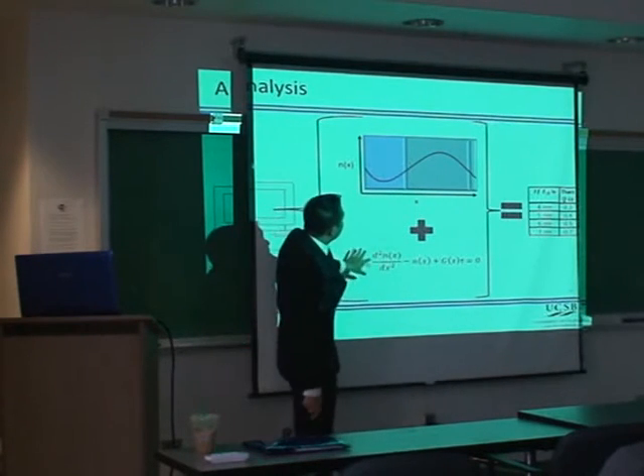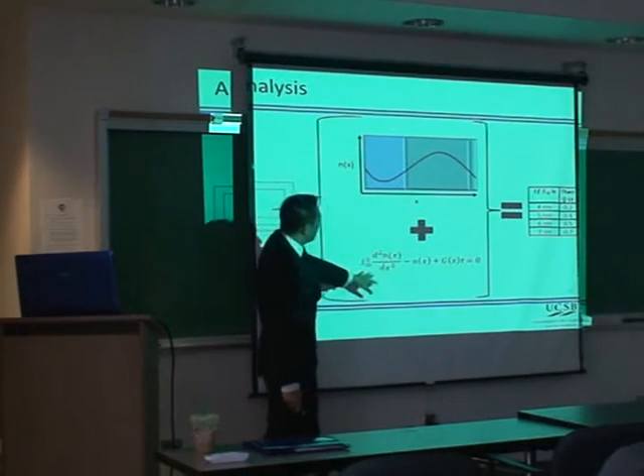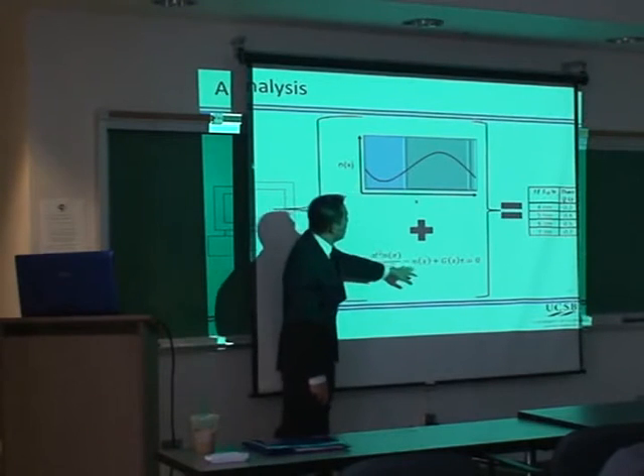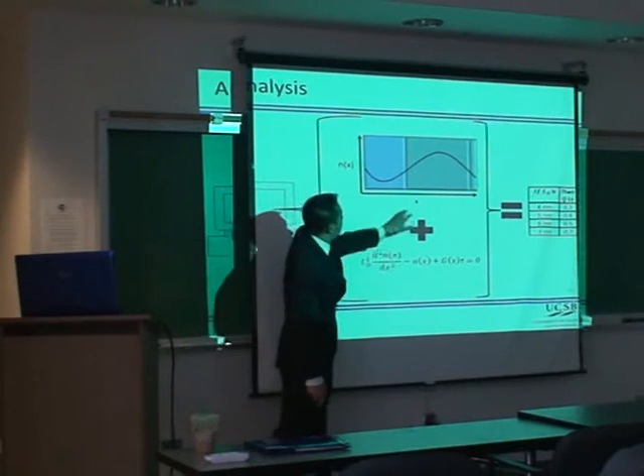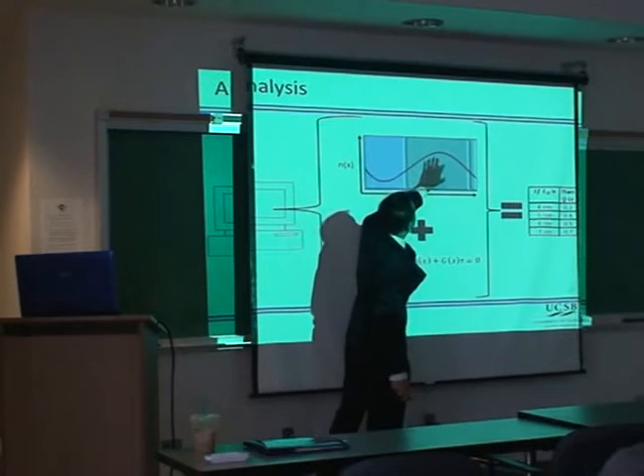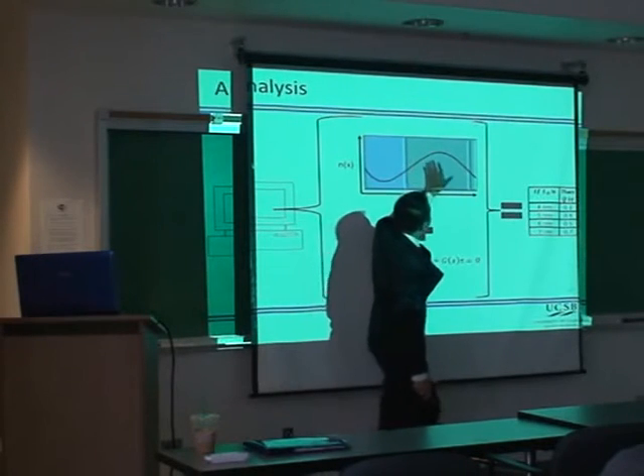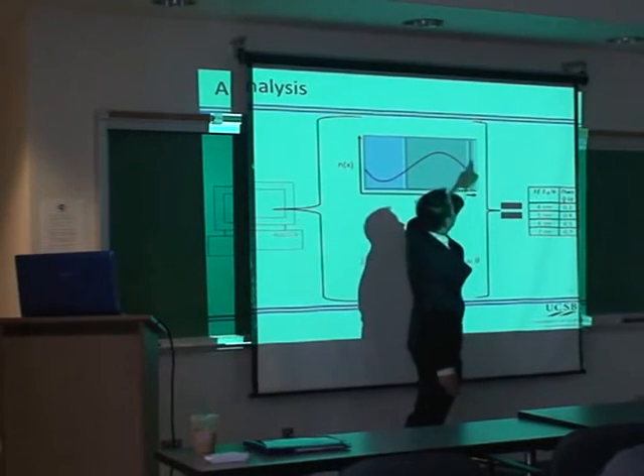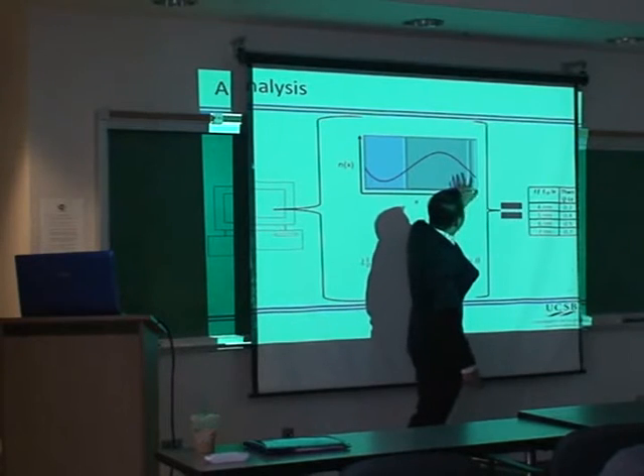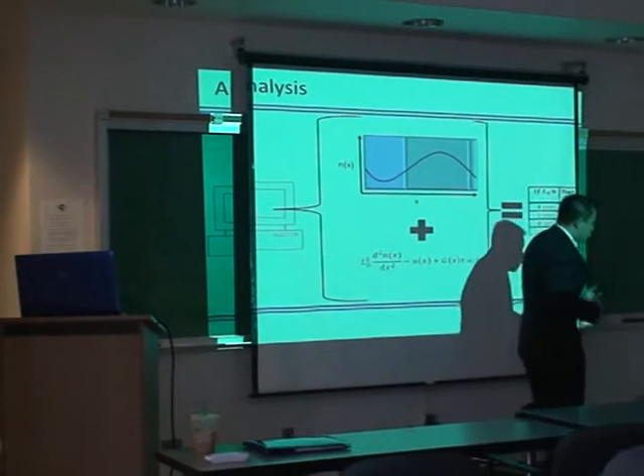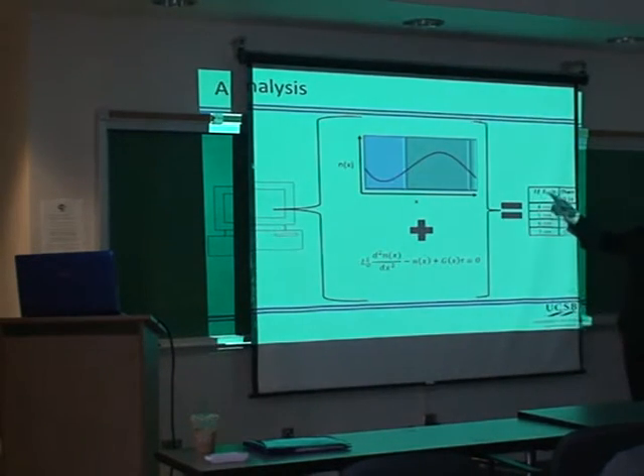So to model this diffusion, we use this partial differential equation, which is able to predict how these excitons will migrate from higher concentrations to lower concentrations, and how many of them will reach this interface, which is the quenching interface. And therefore, what the model does essentially is that it chooses different exciton diffusion lengths, and it predicts what the quenching efficiency would be for each of those.